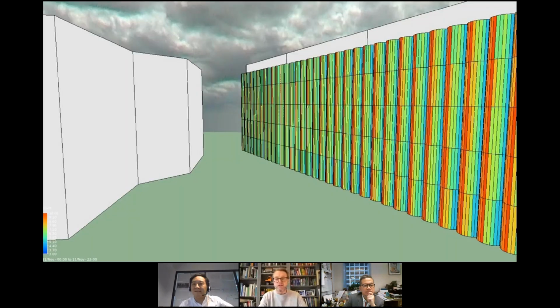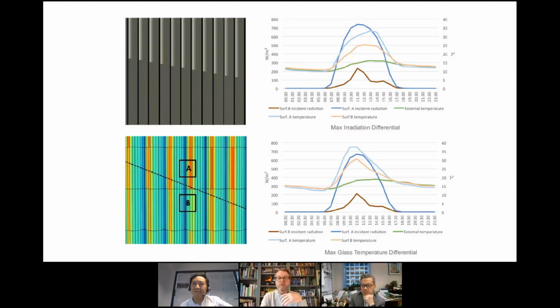So here you can see a slide which tries to illustrate and break down into bands where we see the most irradiance on the glass itself, where the glass is seeing the most light heating it up. At the same time, behind that is the ambient temperature of the air itself. So we look at the combination of the energy from light heating the glass locally relative to the sun angle and how that hits the glass, as well as the ambient temperature. And then we look at how that breaks down into stresses in the glass.